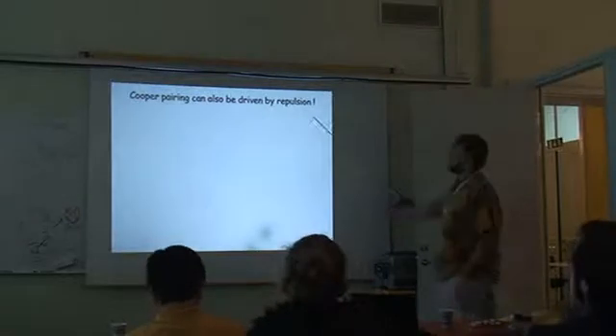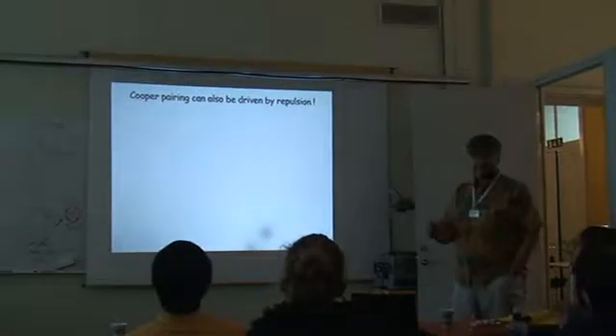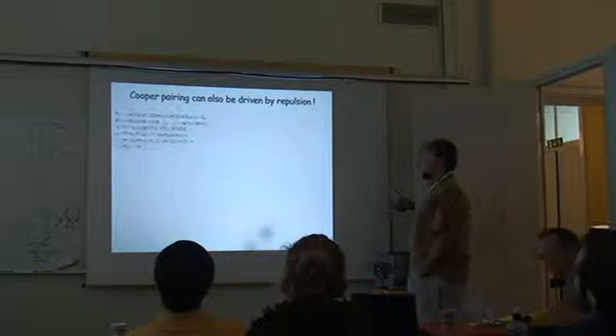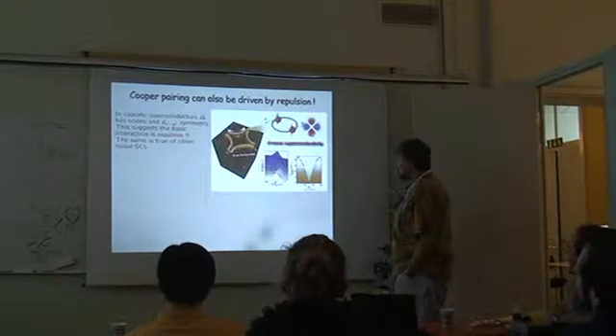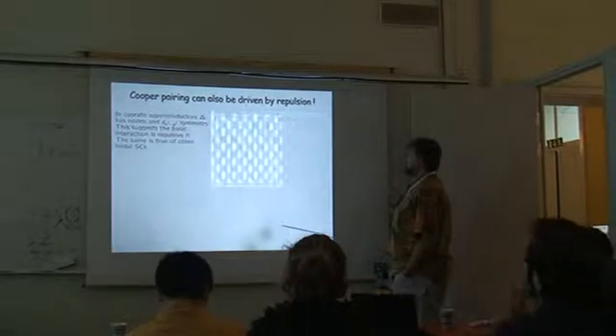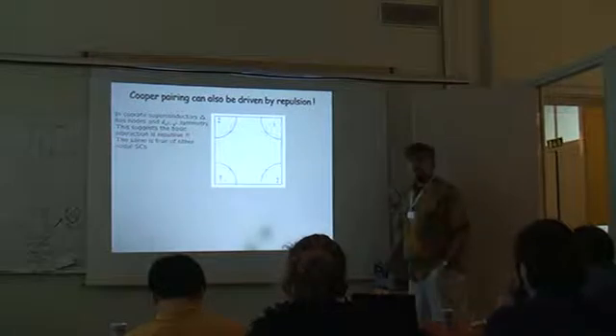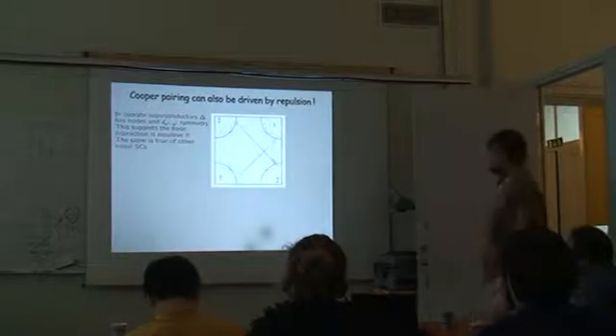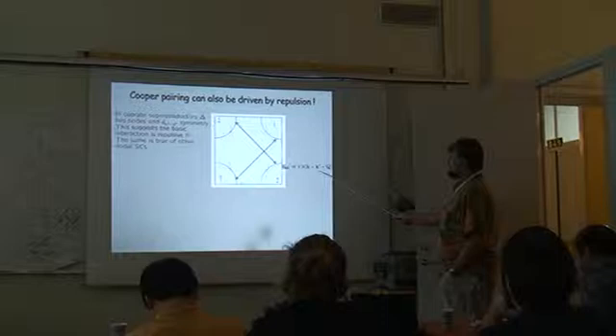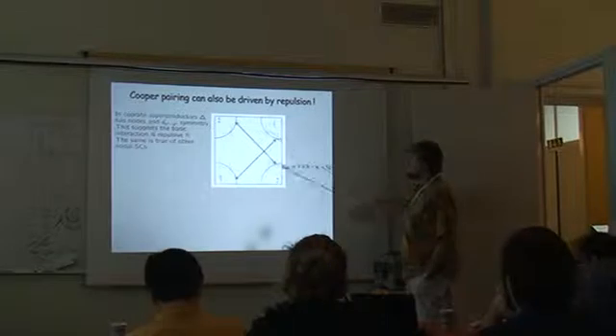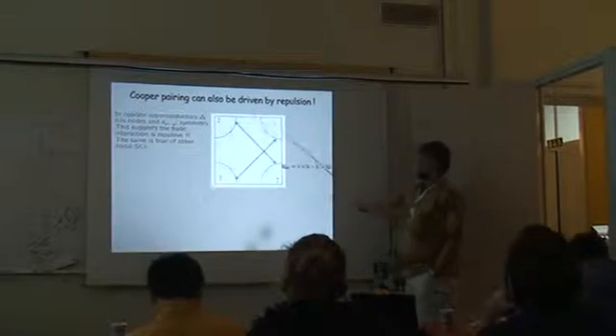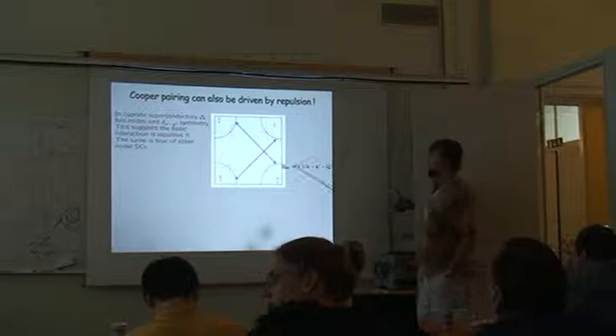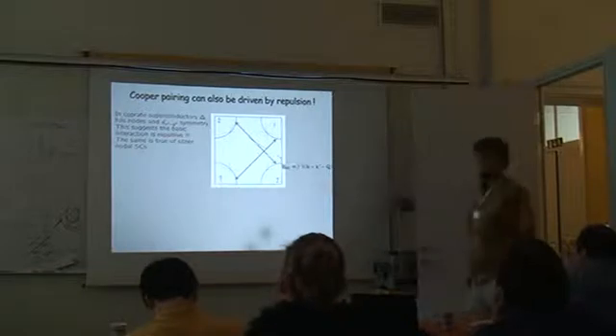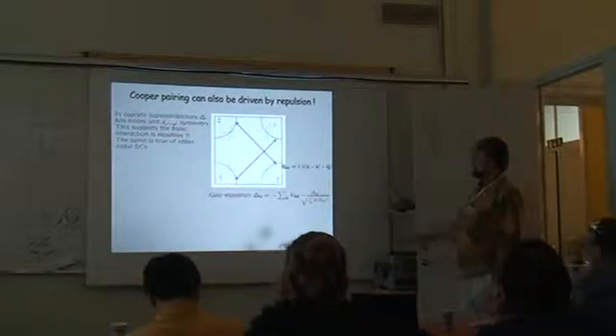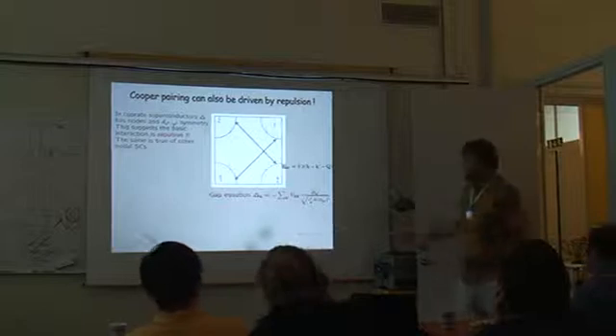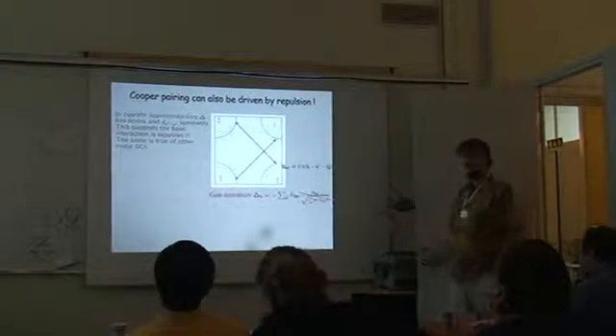Now, Cooper pairing can also be driven by a repulsion, as Professor Raghu showed us this morning. In that case, like say in cuprates, we have a d-wave-like order parameter. How can you get Cooper pairing from repulsion? Well, if the interaction is repulsive but concentrated in momentum space, so that it connects portions of the Fermi surface with a wave vector that's close to this green wave vector, then you can solve a gap equation, which now has an annoying minus sign here, so an s-wave solution would not work.